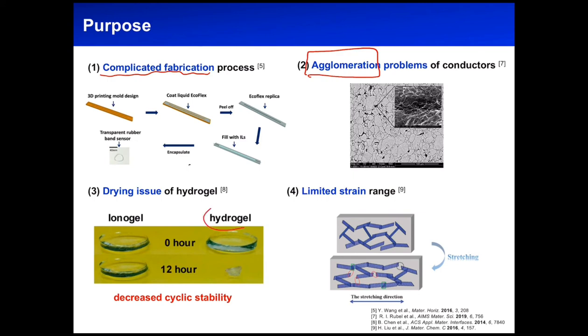Moreover, hydrogel-based sensors also suffered serious problems such as drying issue, which decreased the cyclic stability in ambient condition. Therefore, they need additional encapsulation process or should contain humectants to prevent water drying. More interestingly, conductive material-based elastomers have a limited length to endure the applied strain due to the discontinuity of the conductive channel. Therefore, in this study, we focused on the highly stretchable materials based on copolymeric ion gel.